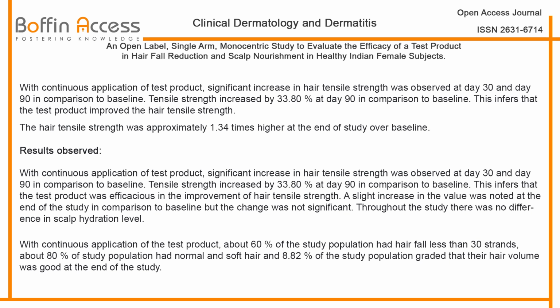Results observed. With continuous application of test product, significant increase in hair tensile strength was observed at day 30 and day 90 in comparison to baseline. Tensile strength increased by 33.80% at day 90 in comparison to baseline. This infers that the test product was efficacious in the improvement of hair tensile strength.